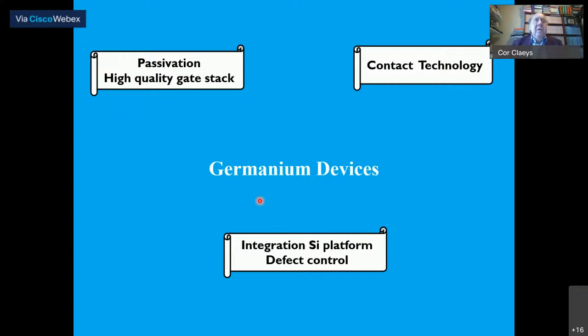But if you want to put germanium on silicon, you're going to deposit epitaxially 2 materials with a different lattice constant. That means there is lattice mismatch. And for silicon germanium, the mismatch is 4%. And mismatch means that you have defects. And you have to optimize your processing in order to minimize the defect generation. You cannot bring it to 0, but you have to minimize it so that you're not going to see the impact of your defects on your device performance.